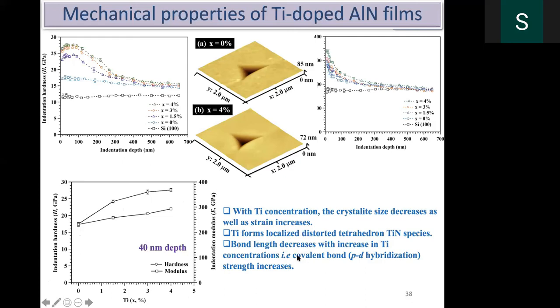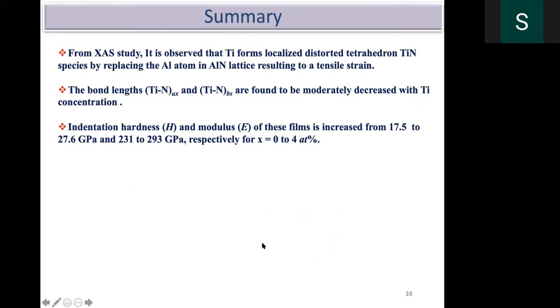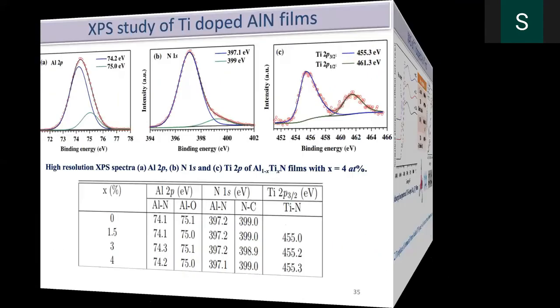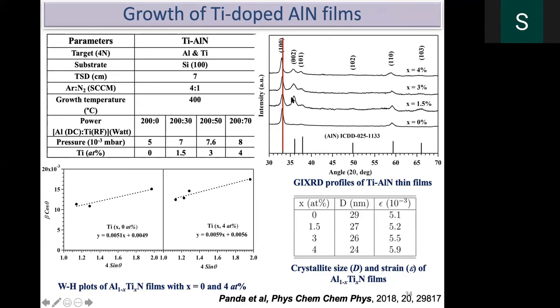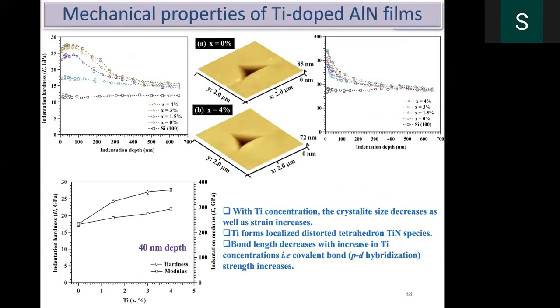The bond length decreases with the increase of titanium concentration. From this, we can understand. So the summary is the titanium replaces the aluminum atom, and because of that, a tensile stress forms. That also can be understood from the shift in the peak. When the peak shifts towards the left-hand side in 2 theta, that means d increases. That means a tensile strain in the system. That's what we can understand from the X-ray. All those things we have to compare, then we can come to a conclusion.